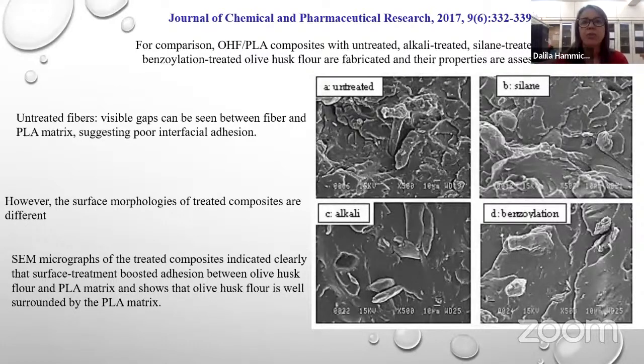However, the surface morphologies of the treated composite are different. Indeed, the treated fibers are coated by layers of matrix materials that considerably reduce the gaps between them. It is also observed that the layers of materials are pulled out together with the fiber during impact fracture, which further substantiates adhesion between the fiber and the matrix. The same analysis indicates that the matrix-fiber interface is better defined with treated olive husk flour. The micrographs of the treated composite indicate clearly that the surface treatment boosted adhesion between olive husk flour and the matrix, and show that the fiber is well surrounded by the matrix when we use the treatment.